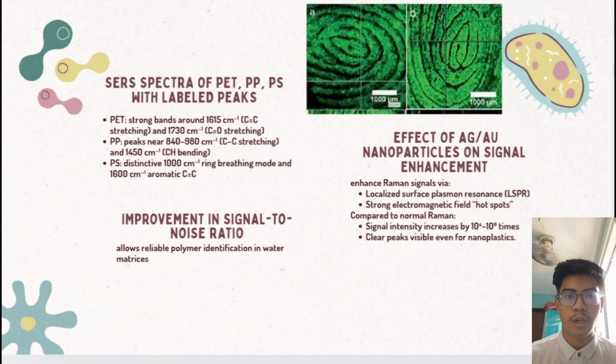In the case of polypropylene, characteristic peaks appear near 840 to 980 inverse centimeters due to carbon stretching, as well as around 1,450 inverse centimeters from CH vibration. Polystyrene exhibits very distinctive features, especially the ring breathing mode at approximately 1,000 inverse centimeters and aromatic C=C stretching at 1,600 inverse centimeters. These signals are dramatically enhanced when silver or gold nanoparticles are used as